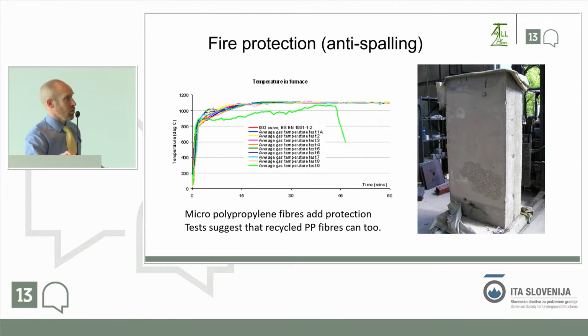On that subject, you're familiar with the fire tests. You have a particular fire curve. Obviously, as we know, unfortunately, the heat that you get inside a tunnel is tremendous, very high temperatures. You're hitting 1,000 degrees. And the problem with normal bar-reinforced concrete is that we make very good concrete. That means it's very dense. There is still water in the pores of concrete, and when you heat up a very dense concrete, the water turns to steam, and the danger is that this causes an explosive spalling.